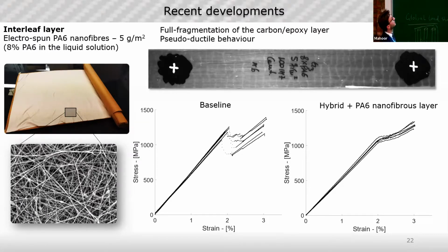Putting this nanofibrous layer is just like applying it on the prepregs, putting the rest of the glass plies on top of it, and the material is made. And the good thing is also that it doesn't affect the final thickness of the material, because this layer will absorb the resin of the surrounding fiber reinforced layers, and it's kind of compressed. Of course, it's produced in autoclave, so with 7 bar, but instead of using the resin film or the thermoplastic film, with this approach, we may keep the thickness of the material constant and not affect the initial stiffness.